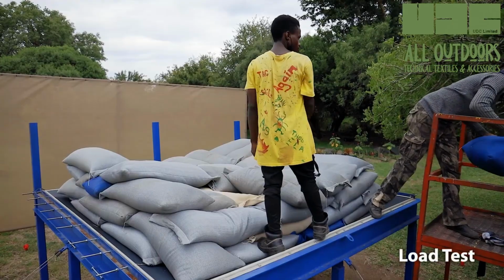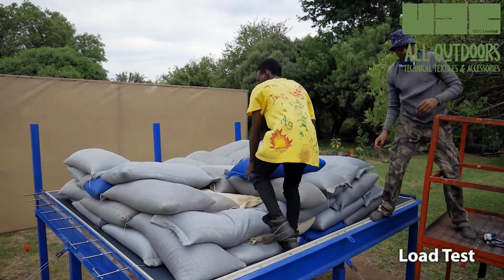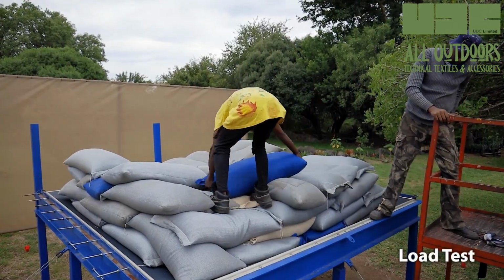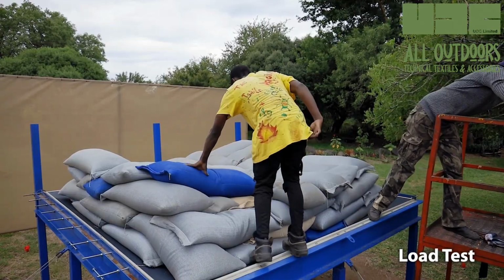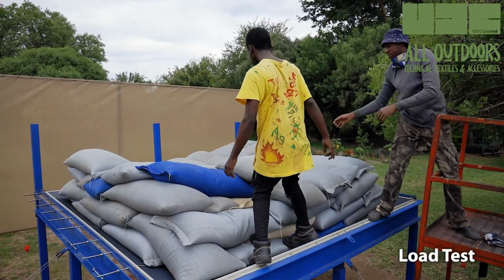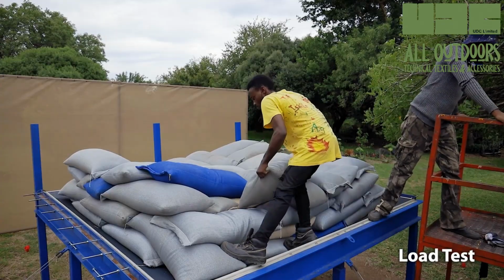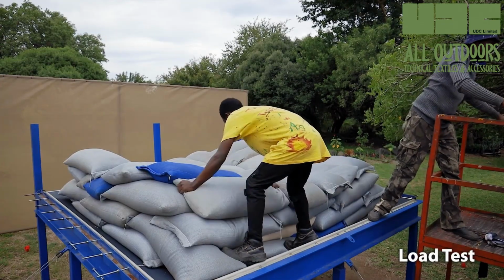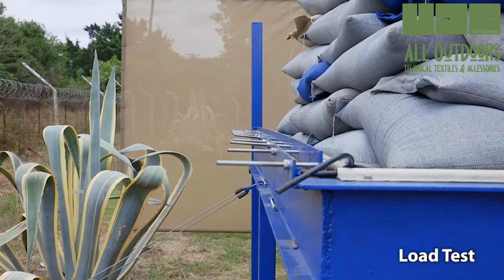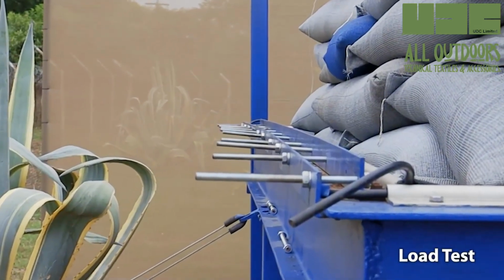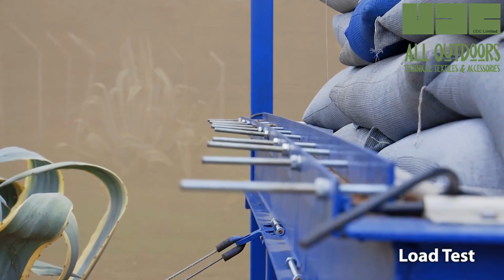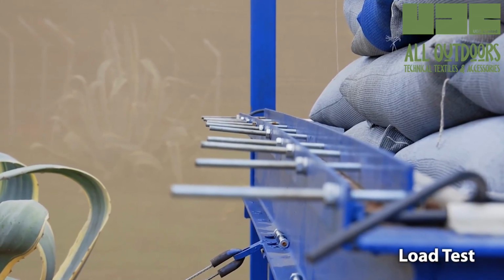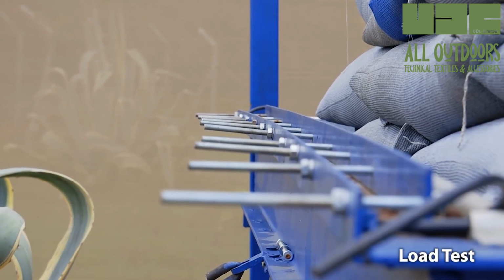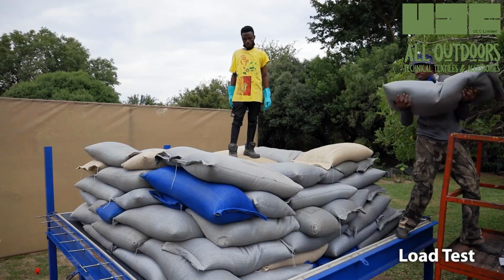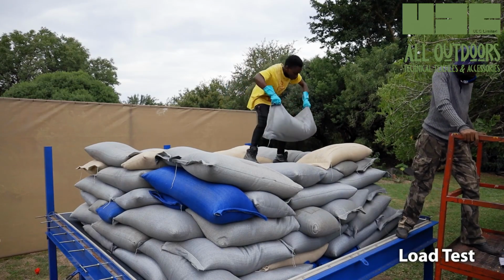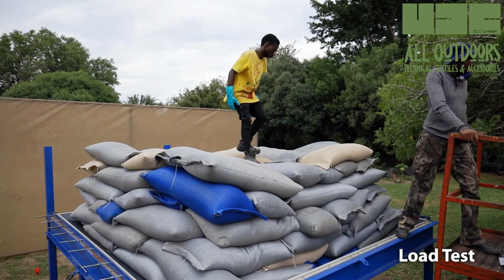For the load test, an industrial I-beam frame was constructed to conduct this field test. Extreme 32 fabric was secured by Keder railings on all sides. 25 kg bags of HDPE were then loaded onto the fabric. At 4,000 kg, the top flange of the I-beam started bowing inwards due to the load. An additional anchor was then secured to the top flange to prevent further bowing. We continued to load the net up to 5,000 kg with no failure occurring.